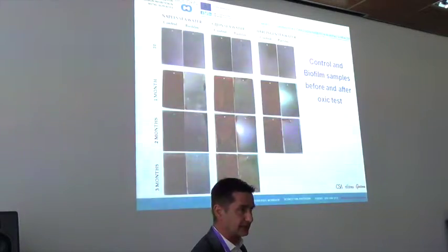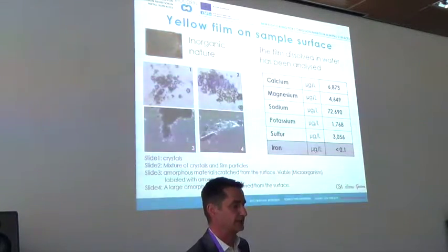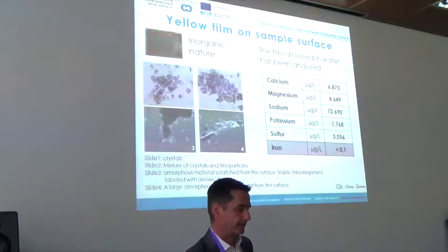We analyzed this biofilm, and it was of inorganic nature and without iron, so not rusty, but there are a lot of ions that are normally present in the seawater: sulfur, sodium, magnesium, and calcium. And with the electronic microscope, we have detected also different amorphous crystals.